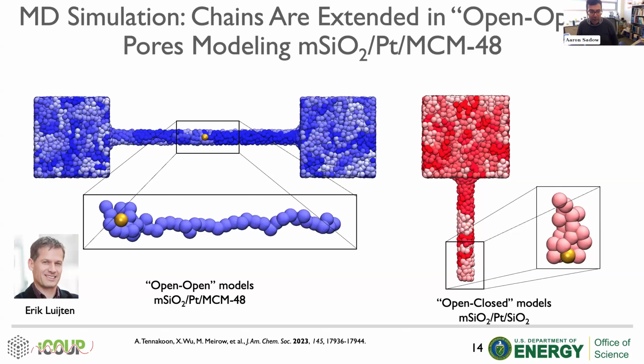So we tried to understand a little bit about why we were getting longer chains. And the way we did that was through molecular dynamics simulation models. This was done by Erik Luijten's group at Northwestern. What they showed was that when you have a system with an active catalyst site in the center of a pore, like we do in this porous core system, then the polymer chains tend to stretch out more.